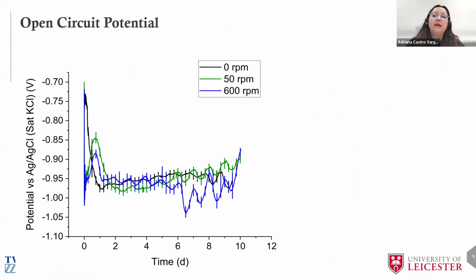Here we can see the records of the open circuit potential and the scans of LPR over time in the 3 different cases. At the beginning of the immersion, we have a drop of the potential. It happens because the oxide layer formed on the aluminum is activated, and it's clear that in all cases the system reached the protective potential for carbon steel. In stagnant conditions, we observe similar things to what we have reported before: slow activation and a kind of stabilization of the potential.